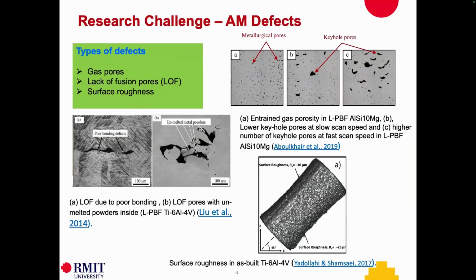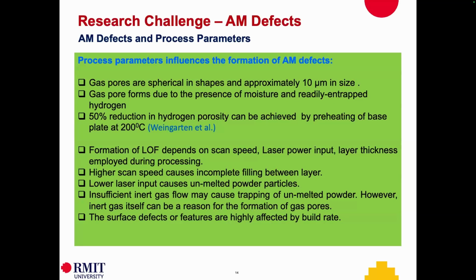Now, lack of fusion happens due to poor bonding. Because of the unmelted metal powders, which stay due to poor bonding, you can create what we call lack of fusion, and you can end up with these unmelted metal particles or agglomerates. We call them satellites. Now, that's the type of defect we need to deal with when we are dealing with AM components. Finally, the surface roughness, which is well known to us. Surface roughness affects fatigue performance. The way the AM process affects surface roughness, we need to understand and probably produce surfaces which are free from crack initiators or roughness defects. So this is a kind of summary of the challenges I described.